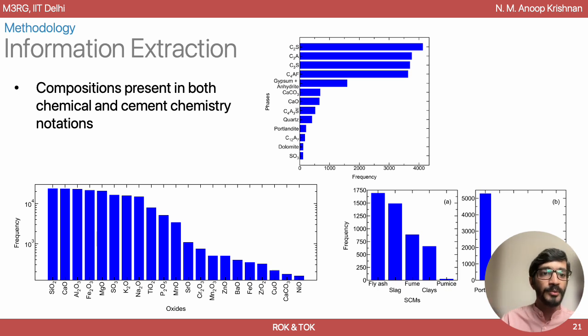So we were actually able to obtain more than 20,000 compositions from the literature using this approach. So this includes C2S, C3A, C3S, etc. This is the cement chemistry notation, and this is the real notation where you have SiO2, CaO, Al2O3, Fe2O3, etc. And beyond that, you can have supplementary cementitious materials like fly ash, slag, silica fume, clays, and pumice, and all of those kind of things extracted from the literature.